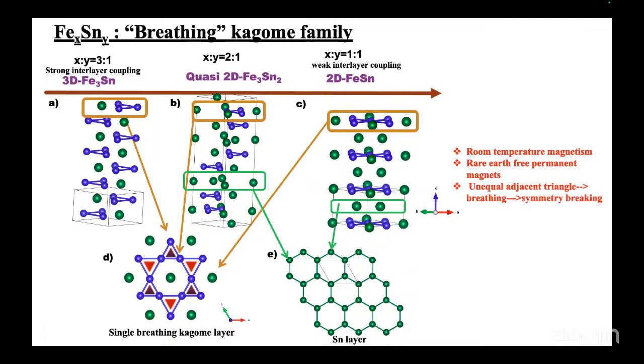And also, the term breathing comes from the unequal size triangles in the Kagome layer, which further breaks the symmetry of the system and also modifies the band structure and magnetism, adding more features to the band structure, along with the presence of moderate Coulomb interaction. And the recent seminal paper highlights how the correlation and the geometry of the system combine and induce the chances of fractional quantum Hall effects, which further motivates studying this system more intensively.